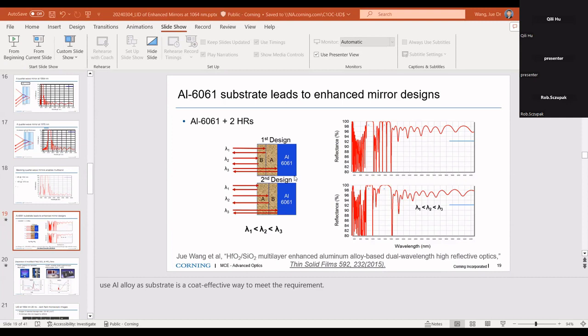Okay, sorry. So by combining the multi-stack put on the diamond and aluminum substrate surface, basically we can make a multi-band mirror. And also for the mid-wave IR, we do not require thicker coating, things like that.